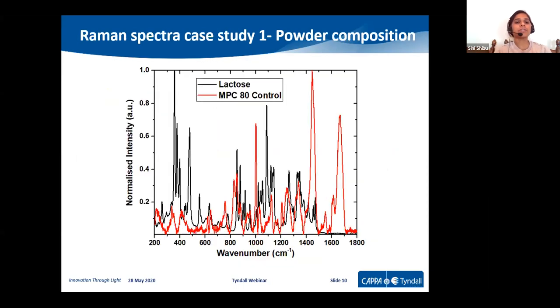In case of Raman spectra, it is actually a complementary technique to FTIR spectra because some samples are Raman active. So we can see some peaks in the Raman spectra and some other complementary peaks in the IR spectra. So that's how we are coming to a conclusion. These peaks are because of this particular component in the material, in the sample.